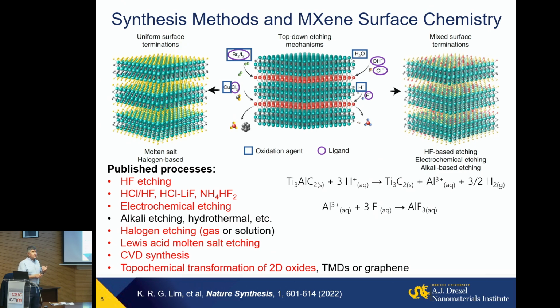So these layers of carbide are actually strongly bonded. The titanium aluminum bond, for example, in this case is a strong intermetallic bond. You cannot shear and break it easily mechanically. So unlike graphite or molybdenum disulfide or boron nitride, you cannot simply mechanically exfoliate them. You have to etch. And we were able to etch this layer. Actually, we can etch it over tens of micrometers, removing a monatomic layer of material.